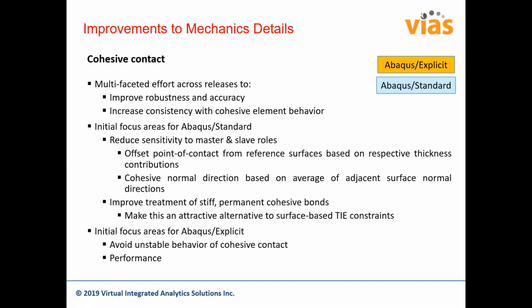Cohesive contact: this is a multifaceted effort across releases to improve the robustness and accuracy in cohesive contact, and also to increase the consistency with cohesive element behavior. Initial focus areas for Abaqus Standard: reduce sensitivity to master and slave roles. So if you interchange them, they shouldn't play a significant role, at least. Offset point of contact from reference surfaces based on respective thickness contributions. Cohesive normal direction based on average of adjacent surface normal directions.